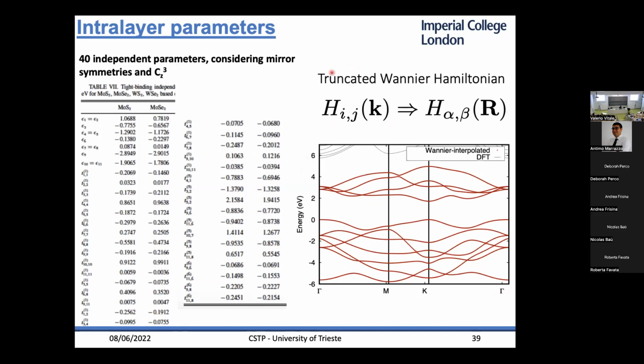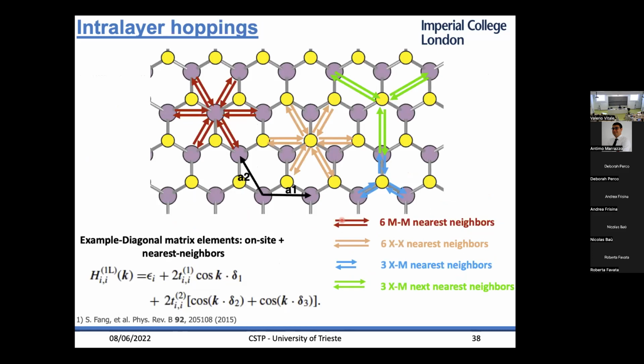Right? So if you want to parameterize this tight binding, you need the on-site terms and then 40 independent parameters, and then you can generate all the other parameters by symmetry. But the reason why we call this tight binding ab initio tight binding is that we take a DFT band structure of the monolayer, we generate the Wannier Hamiltonian in real space, so we do a Wannierization. We generate the Wannier functions, and then we truncate the Hamiltonian in real space, and we only keep the real space Hamiltonian that is compatible with this third nearest neighbor hopping.